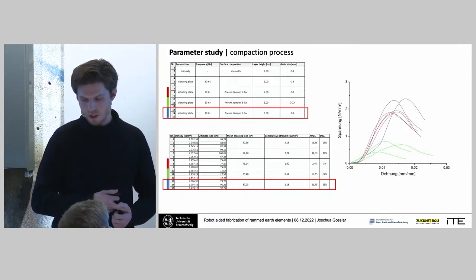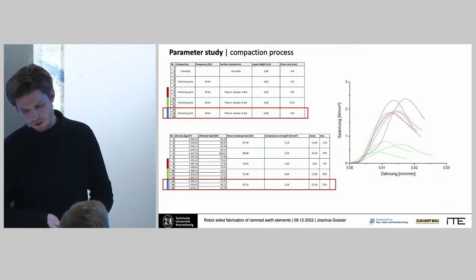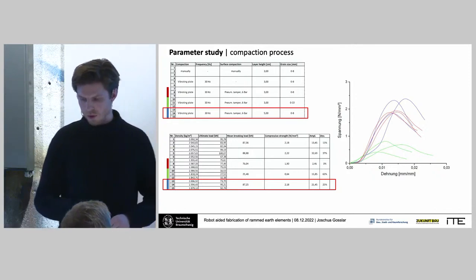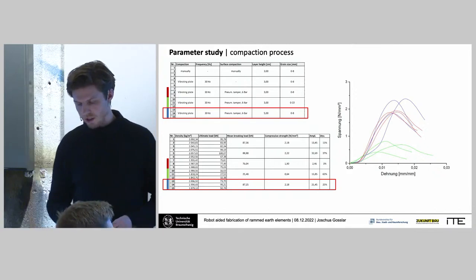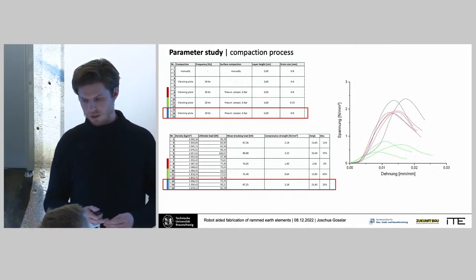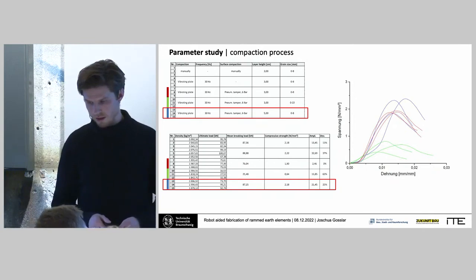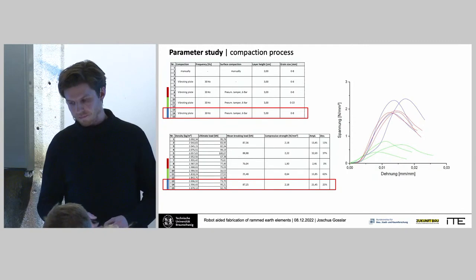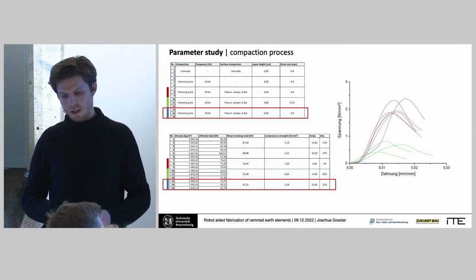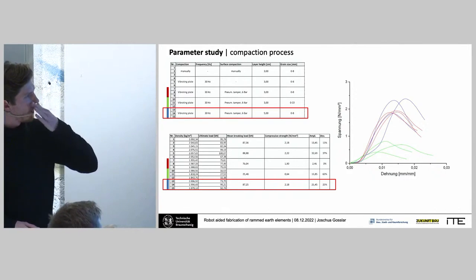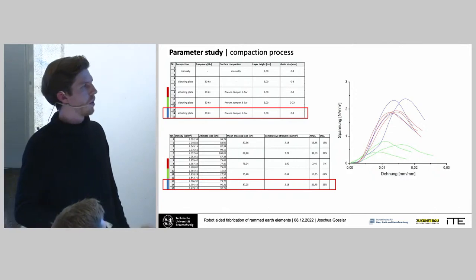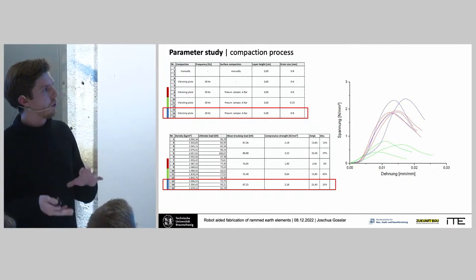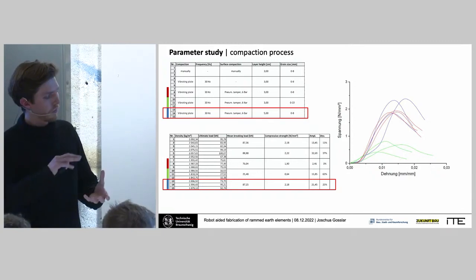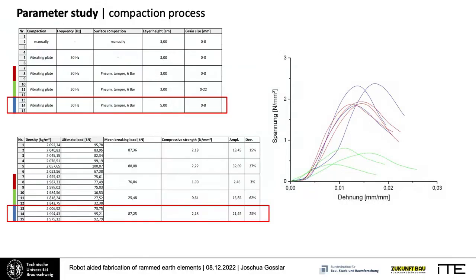Then of course it's a research project. So in order to evaluate the compaction process, we performed some studies with different compaction parameters, because there's quite a broad range, of course, also when we talk about different layer height. So here, I think you're not able to read everything. It's also not necessary. We just performed some tests. You always do minimally 3 cubic test specimens that you test on compressive strength. On the right side, you see compressive strength of different specimens that we did.